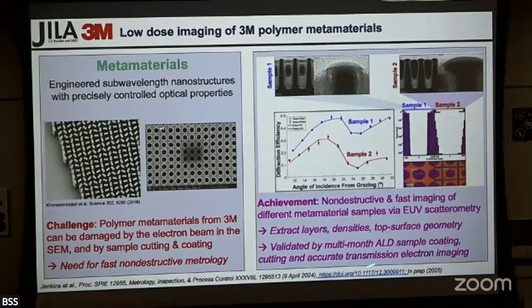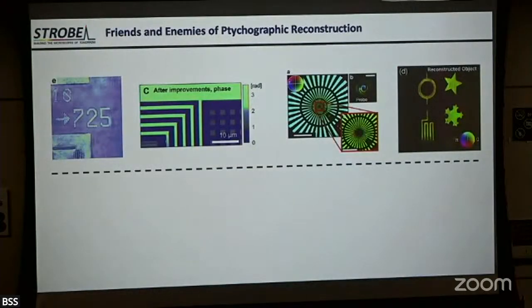And of course, we had to validate this. And so we worked with Steve George's group, who is measurement in a transmission electron microscope, where if you do conformal atomic layer deposition, so do a couple of nanometers of deposition over the metamaterial, as well as deep into its structures, you can preserve the structure. Great for a validation, but it's not a practical metrology. But we were able to show that we got the same results.